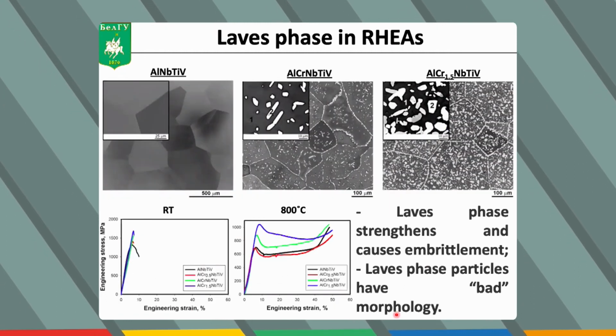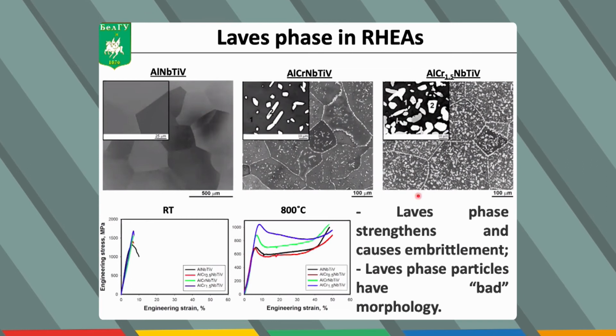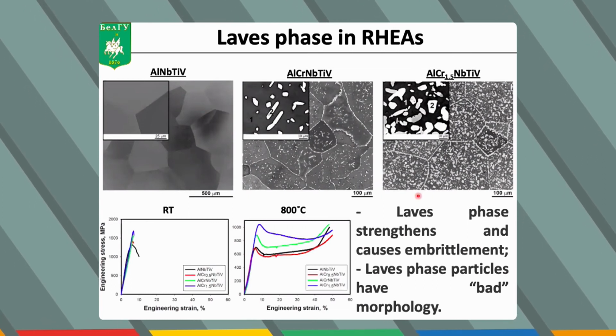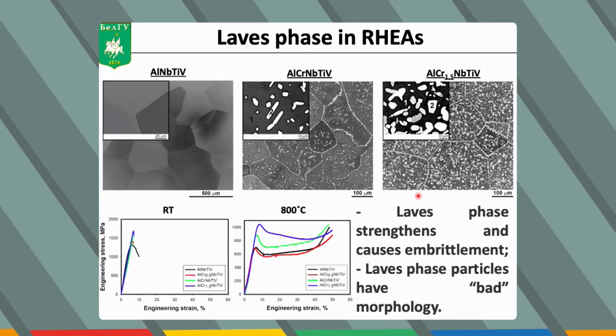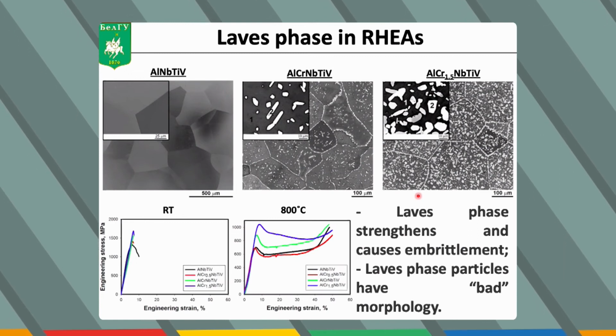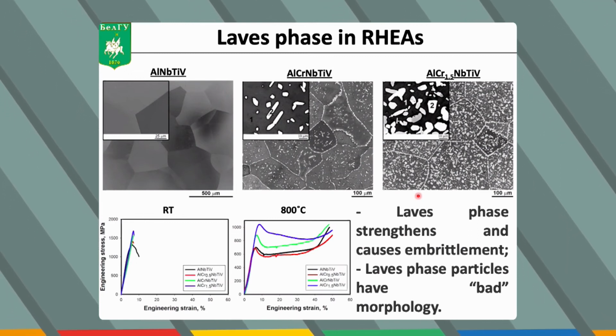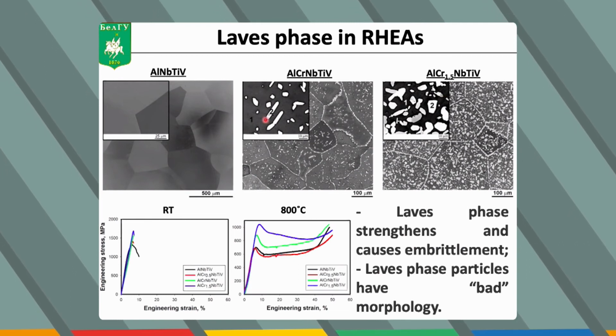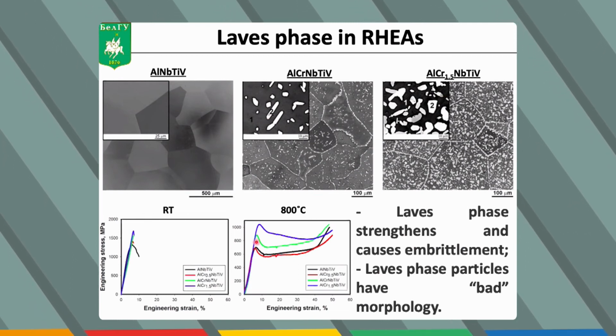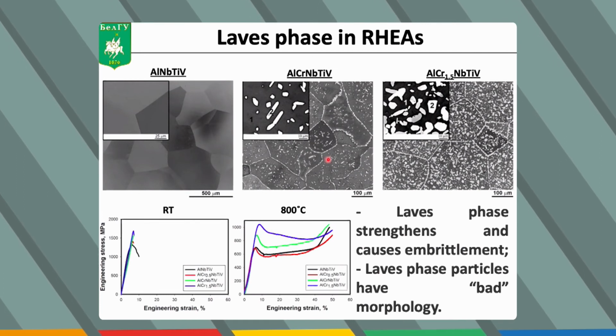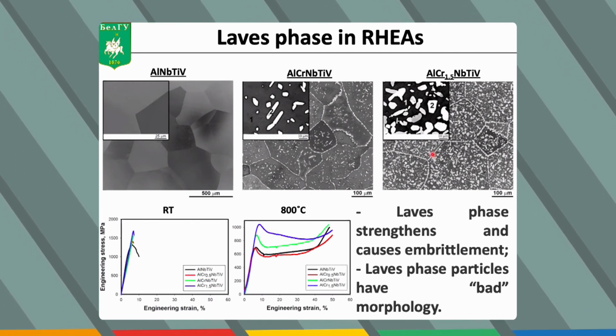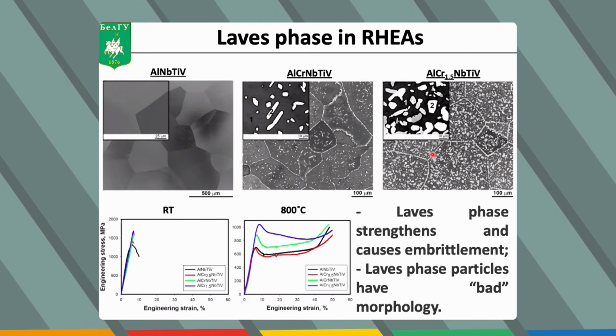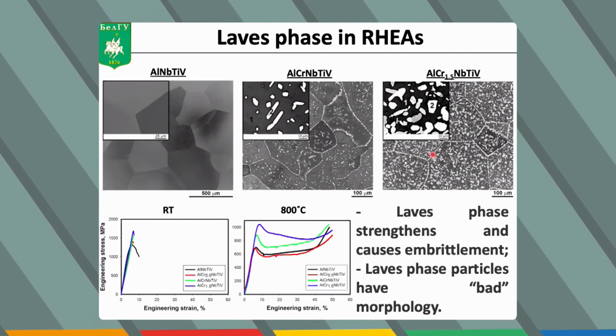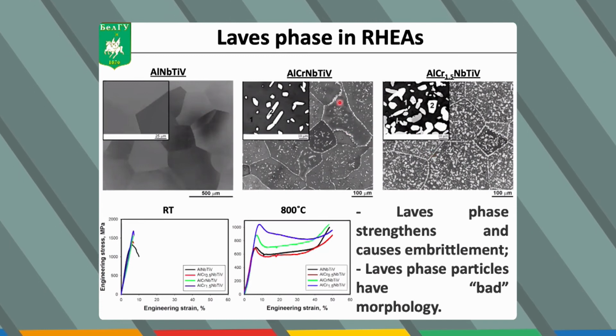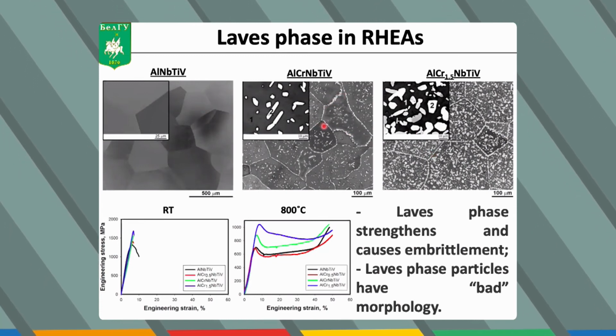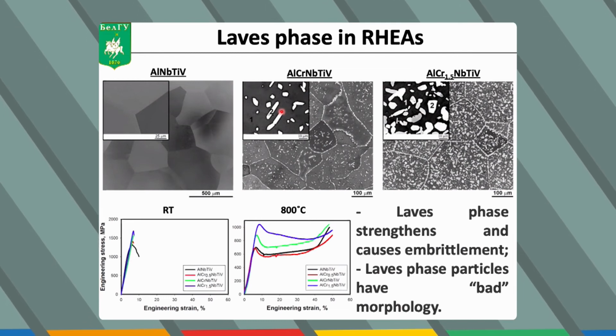But still, what we wanted to do here is to develop new alloys strengthened by fine particles of the Laves phase. Laves phase is quite often found in the refractory high entropy alloys. Some examples are shown here, and it's quite an effective strengthener. But nevertheless, if you look at the morphology of the microstructure, it's not what you want to get if you are looking for nicely balanced properties. You can see the particles are mostly at the grain boundaries, they're coarse, they're irregularly distributed.